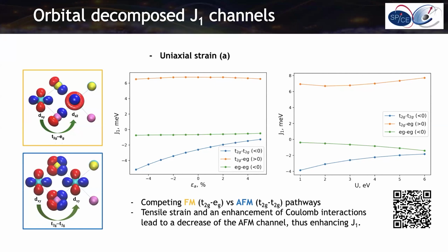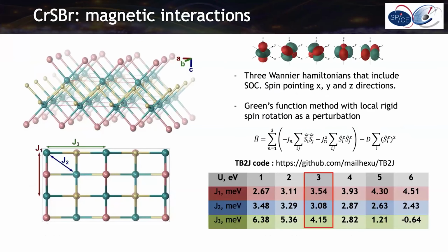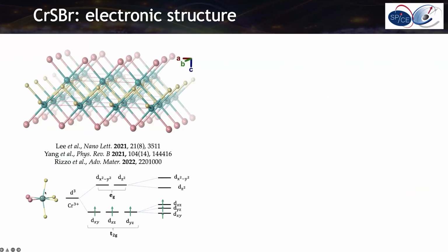No, again, in the ideal system with full symmetry, the diagonal coupling should be zero, because you cannot hop except across a crystal field gap. So it's only t2g. For instance, in chromium triiodide, you don't really have anything but t2g. But in your case, you have both. And in fact, I now realize that t2g is even larger. That's interesting. That's very unusual. Yeah, exactly, this distortion, that's probably coming from this. Okay, all right, thank you.